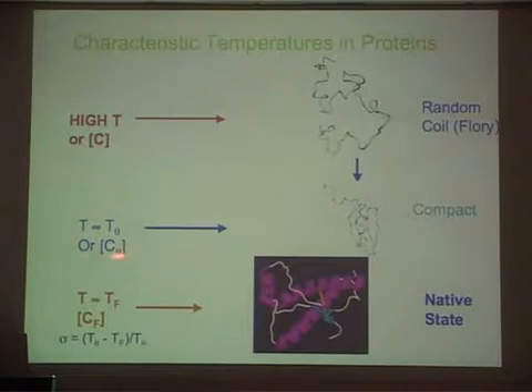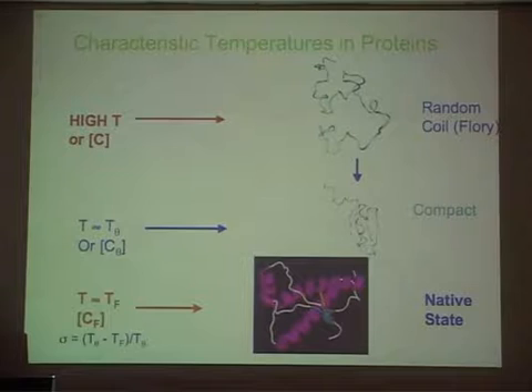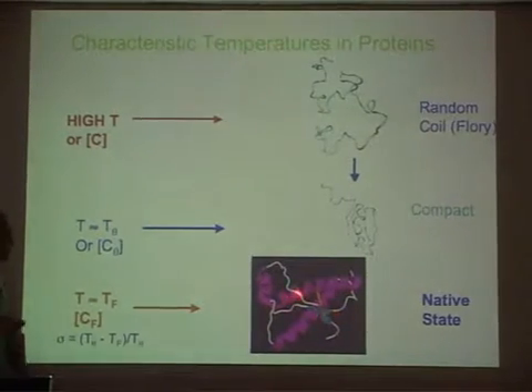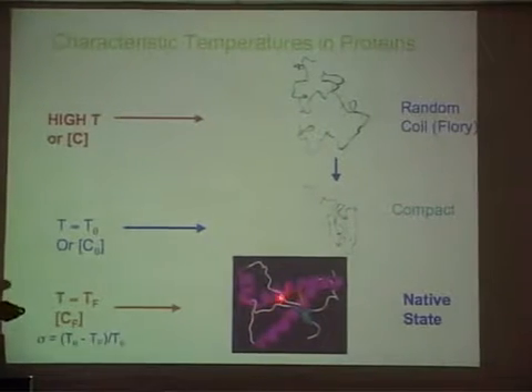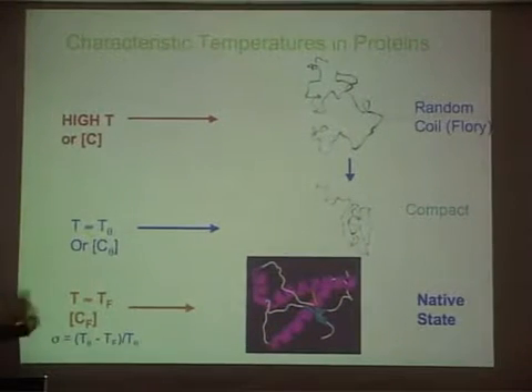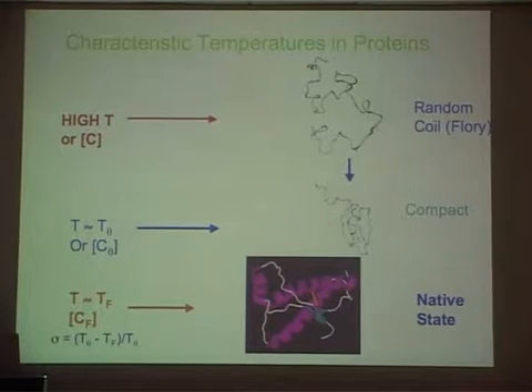If this were the only thing, then the problem is it can't be a protein, because one knows from rigorous polymer physics that the number of compact conformations scales exponentially with the molecular weight, but we know that the native state is relatively unique. And in the language of physics, you would say that there are some discriminating energetic interactions that say this helix should be next to this helix with the residues in this helix making specific contacts. Therefore, there's another phase transition, if you will, at a lower temperature, which I'll call the melting temperature or the folding temperature.